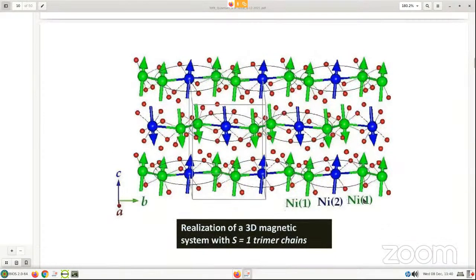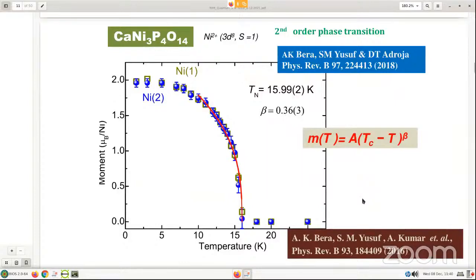So this is the outcome of the neutron diffraction experiment. And we have also done this so-called critical exponent study. What is plotted here is the ordered moment at the nickel site, because in this case only nickel is magnetically ordered, in Bohr magneton per nickel ion, as a function of temperature. This is derived from the neutron diffraction experiment as a function of temperature, and this is the paramagnetic state.